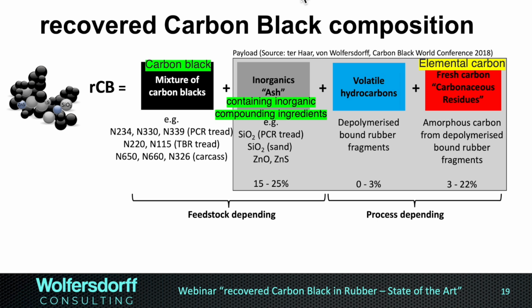And so I said pyrolysis is really contributing less than the feedstock selection to the recovered carbon black. Of course, some of the recovered carbon black producers didn't like it because they need to sell their pyrolysis technology. But when you think of the major components of recovered carbon blacks and the ash content, they really are governed by the feedstock selection.